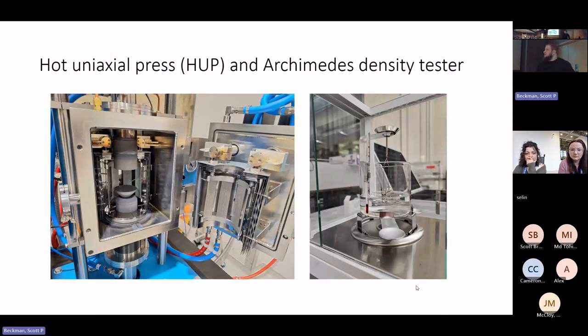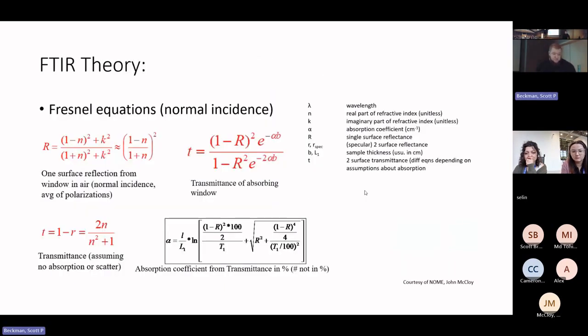So just to give you a little bit of a viewpoint of what we have, that image on, I believe would be your left, is the hot uniaxial press. You can kind of see it's a pretty small chamber, and these rams right here, these are carbon rams, and this is a carbon reducer that we use because our actual die press that we use is slightly smaller than the outside diameter of these rams. And then on the other side, we have our Archimedes style density tester that we use to test the density of our ceramics. So density is very, very important in producing high quality optical ceramics.